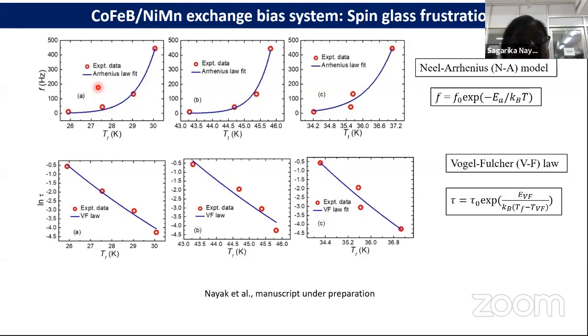So we fitted the frequency versus peak temperature using the Arrhenius law to know if the system is superparamagnetic or spin glass, and the value that we found indicates that the system is not superparamagnetic. So we again fitted the data using the Vogel-Fulcher law, where the Vogel-Fulcher law is defined here, which includes the temperature TVF, which modifies the temperature TF in order to account for any interaction present in the system.